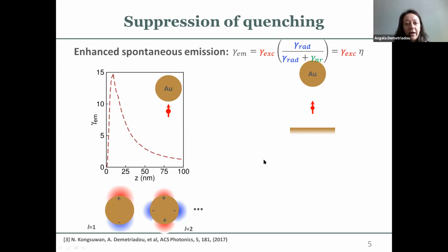When you have an isolated plasmonic structure like a spherical nanoparticle and you put a quantum emitter close to it and you measure the emission rate, which I'm showing the formula for here, what you see is that as I move this quantum emitter closer and closer to the surface of the spherical nanoparticle, you see the emission rate increasing. But when I'm about 10 nanometers away from the surface, you see a depletion of the emission rate. And the reason for that is because, well, we usually say that these kinds of structures have the dipole mode, and that's the one that we usually consider and ignore all the higher order modes.